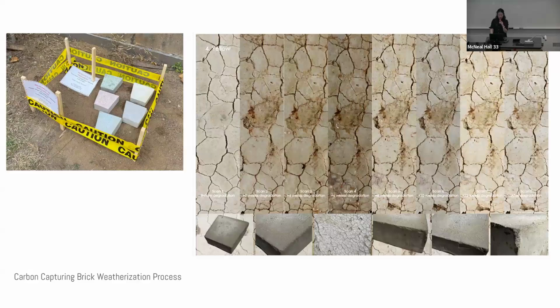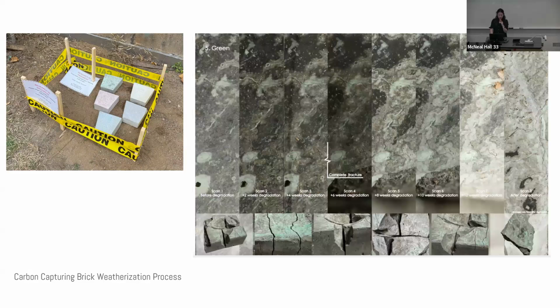This is the yellow one with the most CaO ratio. So in theory, this one is supposed to capture CO2 the most. And this is the green one with just plaster and cement. And so as you can see in these images, each recipe is performing differently, with the bricks displaying distinct degradation patterns based on their composition.